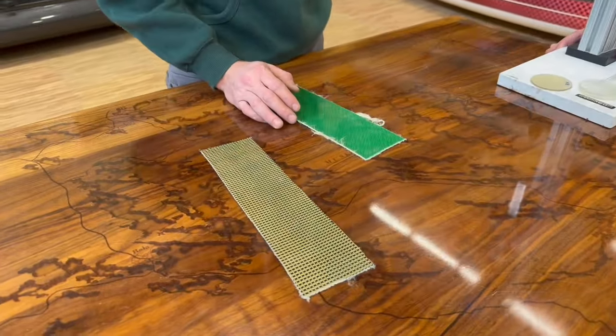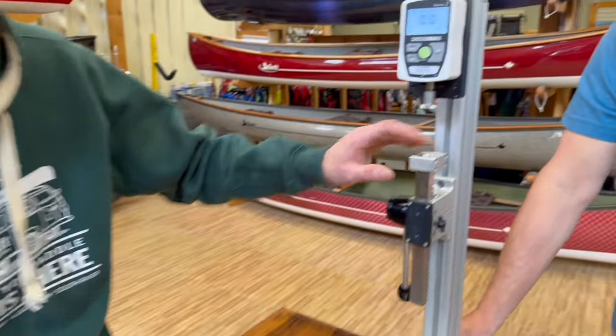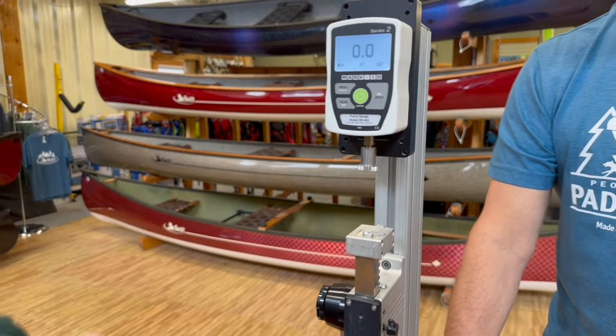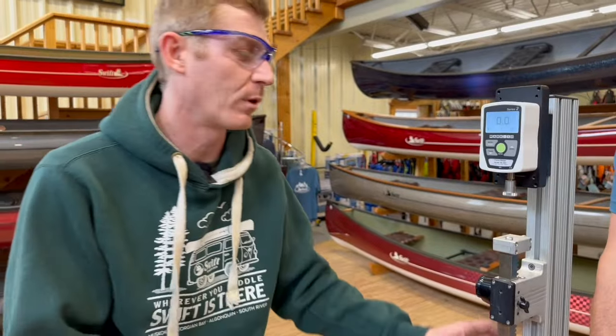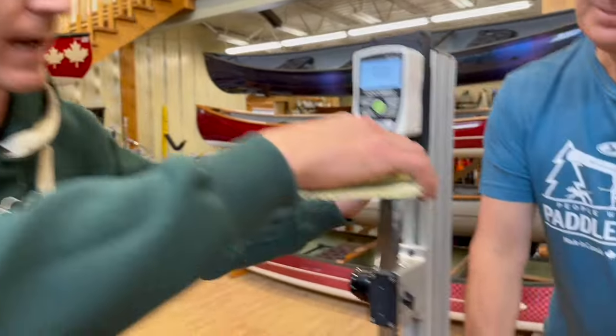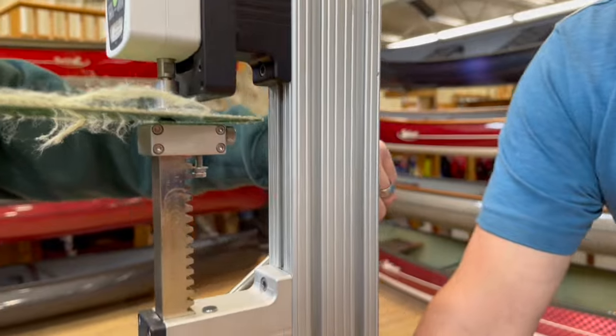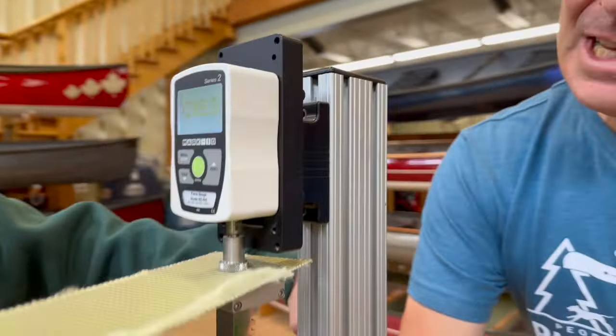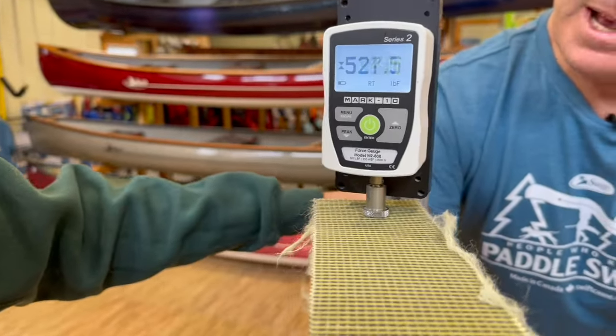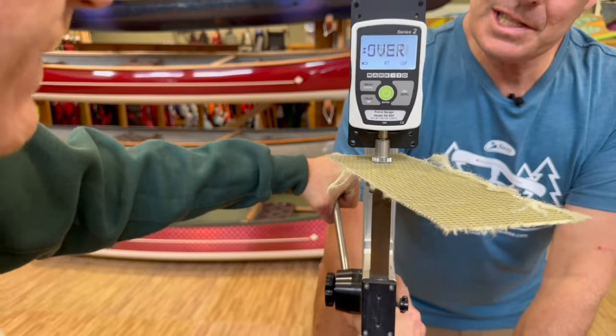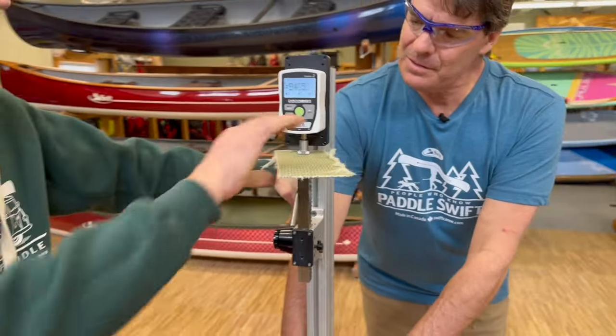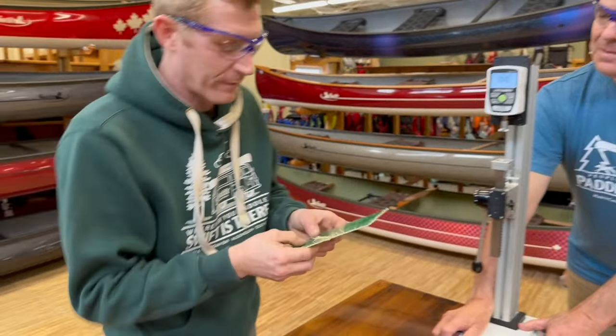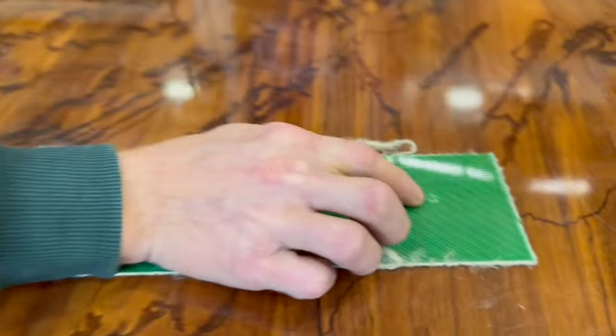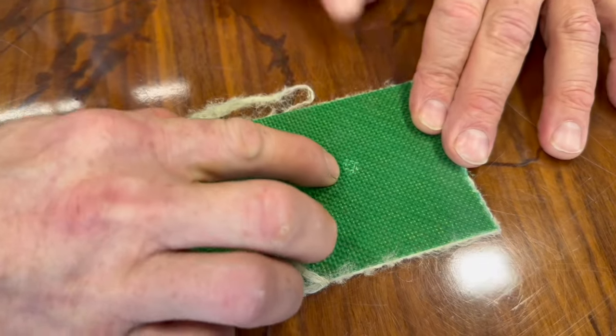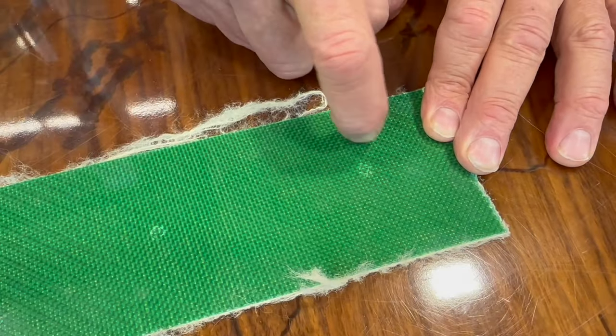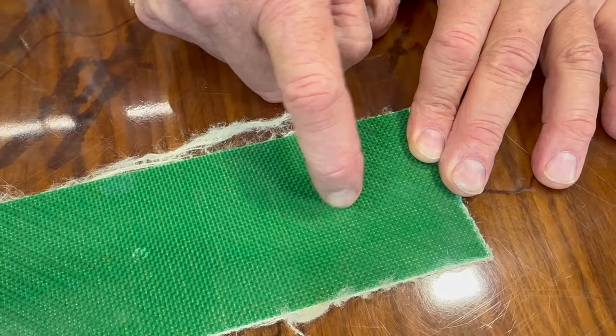So what we're gonna do here is we've created a little pressure point in our force gauge here. We're actually gonna put the finish of our sample on that pressure point, and then now we're going to apply 500 pounds of pressure. And this is our Kevlar Fusion laminate, Matt. Yep. And this one is the standard, our standard build? Yep. So there we go. We've applied 550 pounds of force, and we can see we've slightly cracked the coating a little bit, and we've stressed the laminate just a little bit.